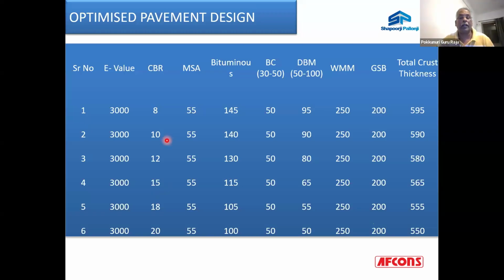So forgetting about that parameter, if you increase your CBR from 8 to 20 for the same MSA, you can see that your total crust thickness is reducing by 5 millimeters. 595 will become 590, 590 becomes 580, and so on up to 550. Meaning what? When you increase your effective CBR of the subgrade by 2%, your total crust is reduced by 5 millimeters. Now, which one is the costlier material in this particular case?